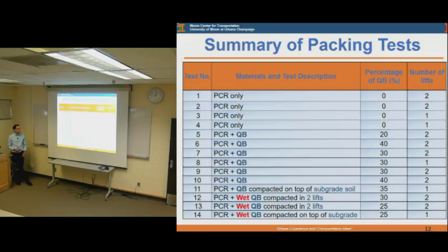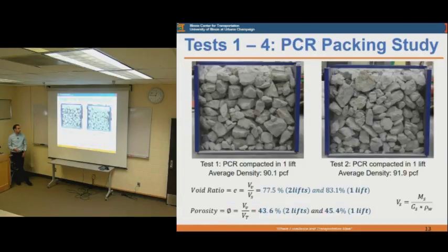And we did some packing tests. So there was a test matrix composed of 14 different tests for just the large rocks and how they pack in the box, then the large rocks with quarry byproducts that were completely dry and varying the amount from 20% to 40%, which is roughly the maximum void content that we have between the large rocks, as well as varying the subgrade or the foundation condition from the steel box into a subgrade soil, soft subgrade soil, and seeing the difference, and also using some wet quarry byproducts because we expect that the material that we get from the quarries will not be completely dry, and how that affects the compaction.